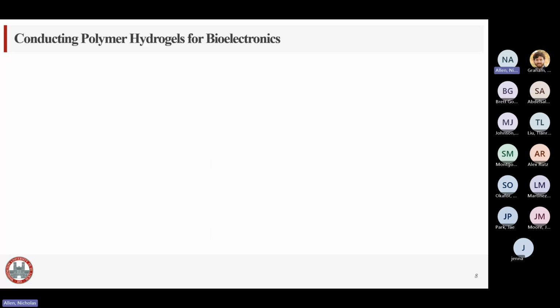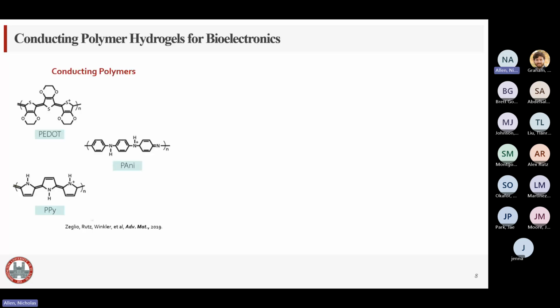Simultaneously, researchers have been developing conducting polymer hydrogels, a different form of hydrogel. These hydrogels are formed from conducting polymer solutions, and these polymers have a conjugated backbone with alternating double and single bonds. And those alternating double and single bonds allow, with a dopant, for electron transduction throughout that backbone. So it has electronic conductivity and can be used at bioelectronic interfaces to transduce signals back and forth, along with the advantages of being soft, hydrated, three-dimensional, and porous like traditional hydrogels.